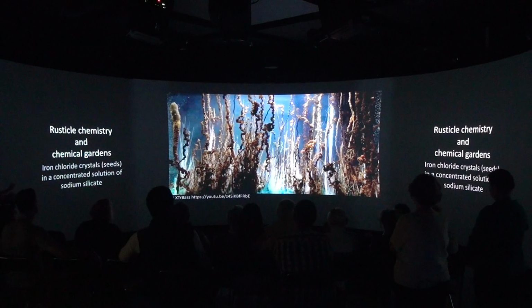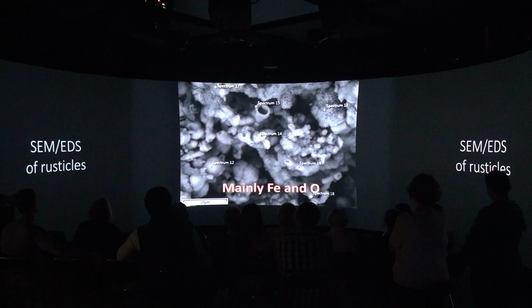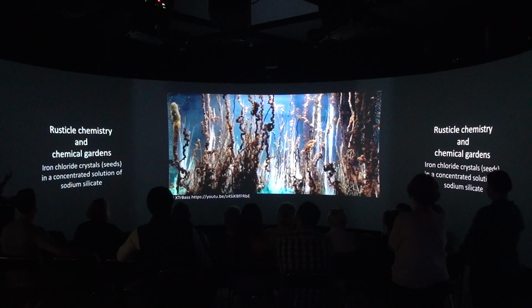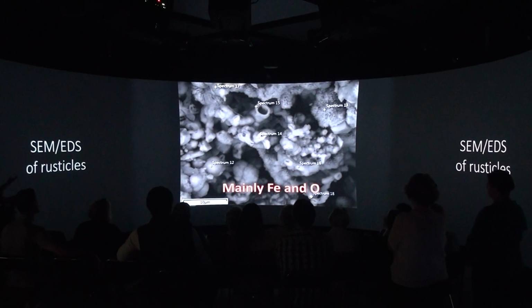So now what I've been telling you about the deep sea conditions, the chemistry of the deep sea, you now know that the silicate increases and all these anionic compounds increase with depth, and the corrosion process can provide a concentrated iron chloride solution that, as I was telling you, leaches out of the rusticles and can start forming these deep sea chemical gardens, as I now call them. So besides the plant-like structure of these chemical gardens, you can see there are like algae growing and floating towards the surface. They can also explain these little microstructures that we used to think were bacteria. In fact, they are really similar to Zeta proteobacteria here. Where is it?